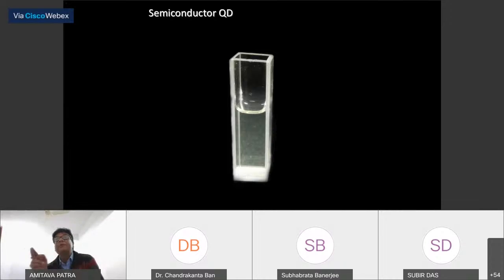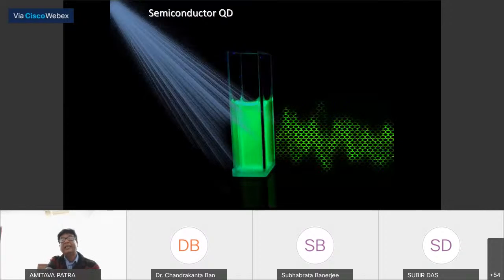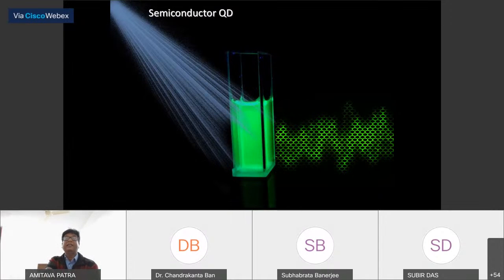You can tune the emission band or the band gap of the material. If you change the band gap, that means you can tune the emission property. For example, this is a solution of cadmium sulfide in daylight, but when you excite it with light, it will generate a green light at a particular size.